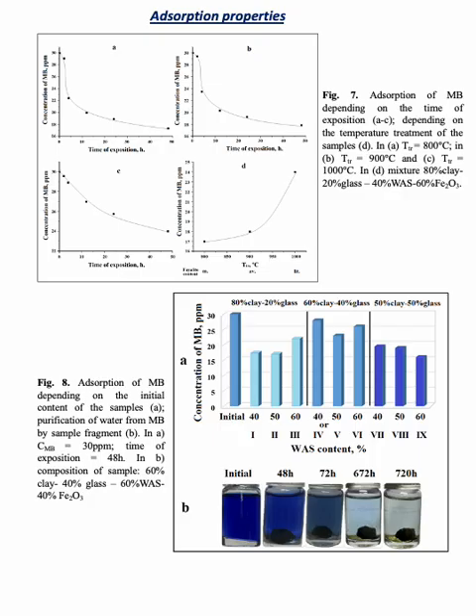The adsorption properties of the samples were determined from an aqueous solution of methylene blue by sample fragments, and we can observe that the adsorption process depends on the initial content of the mixtures and also on the temperature treatment of the samples. Samples treated at 800 degrees Celsius present better adsorption properties in the first 48 hours in comparison with specimens treated at 900 degrees Celsius and 1000 degrees Celsius. The process is slow. Nevertheless, this adsorption process is long and slow and depends on the content of fayalite. From literature, we know that fayalite presents adsorption properties.